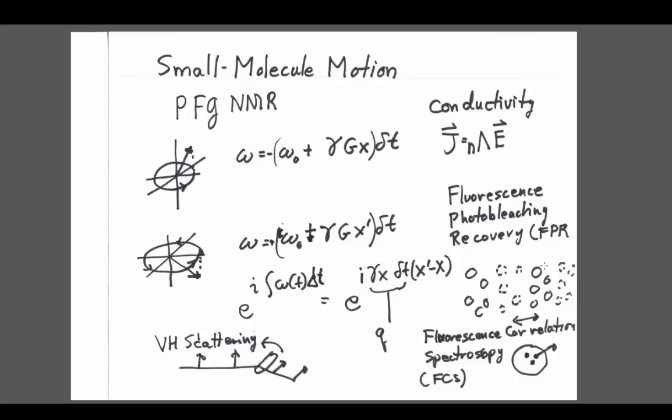We now come to the topic of fluorescence correlation spectroscopy. We look into the solution at a very small volume of solution. And sitting in the very small volume of solution will be some number of fluorescent particles. As time goes on, the fluorescent particles diffuse in and out of the observed volume, which is being hit with the probe laser, so we either count or somehow otherwise measure the presence of the fluorescent molecules.